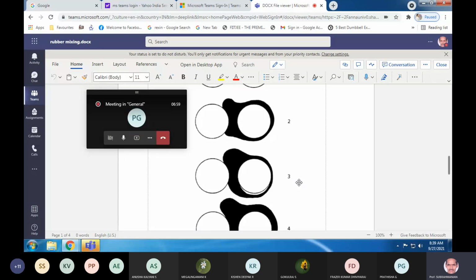This is what we call bagginess. Bagging, or bagginess, it behaves like a sag. It does not cling to the roll, and this separation, known as bagginess, can cause mixing instability that limits the quality of the dispersion.